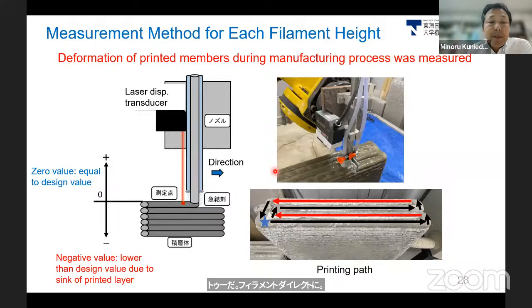And using this system, we try to measure the deformation of the printed members during the manufacturing process, because we should know the buildability of this printing system. So in our lab, we attached the laser displacement transducer to the nozzle, and then measured the distance between the filament and this transducer. As you can see, the zero value is equal to the design value. This is just a target for the printing, but the negative value indicates lower than the design value due to the sink of the printed layer. So we were concerned about the sink of the printed layer, and we measured this distance along all printing paths.